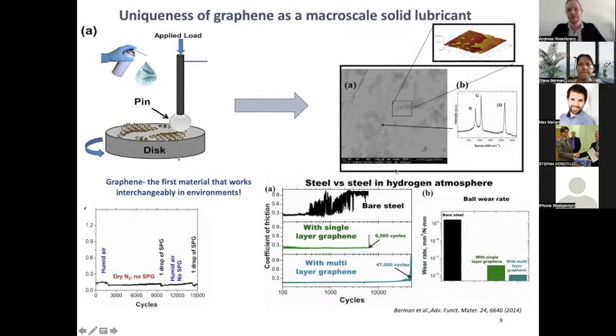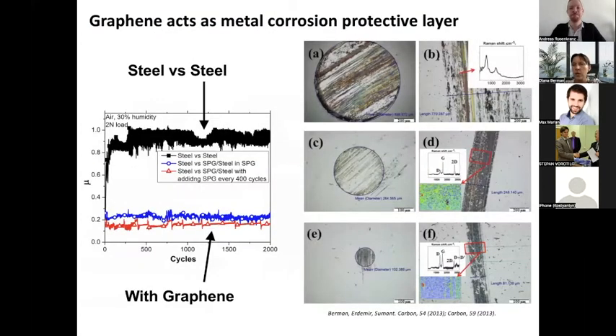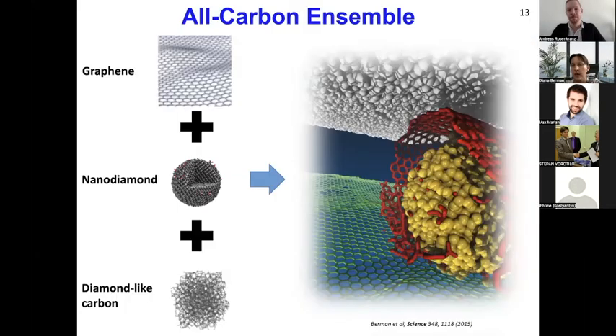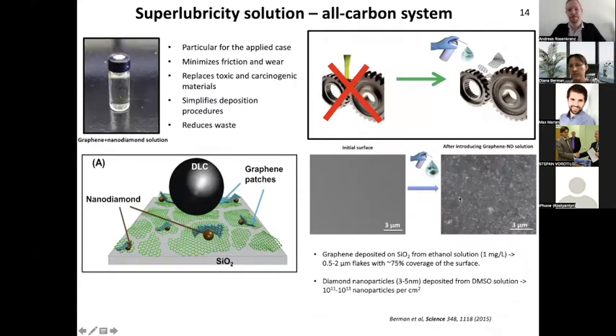Right. And then I got one more question asking, could you tell if the nanodiamond is distributed randomly over the surface or there is some sort of order? No, that's why I showed you SEM images of the surfaces. They're very randomly distributed. I hope it's providing good enough magnification, but you can see that somewhere there are little agglomerates. At some places there are just diamond nanoparticles alone. So here, for example, there are some clusters.